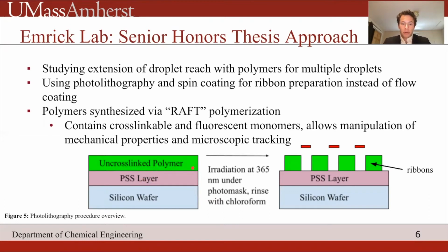Benzophenone cross-links at 365 nanometers under a photomask. And so where these red boxes indicate the photomask, the areas directly beneath them would not be cross-linked, and the green areas, which are exposed to the 365 nanometer wavelengths, would be cross-linked. The uncross-linked polymer is soluble in chloroform, but the cross-linked polymer is not. And so by rinsing with chloroform, we can remove the uncross-linked component from the structure and be left with these polymer ribbons, which are all hydrophobic.